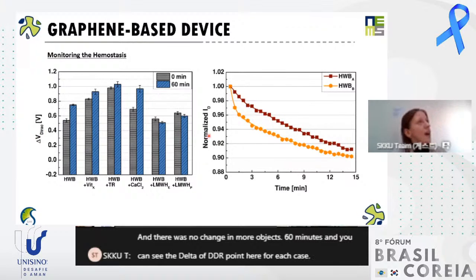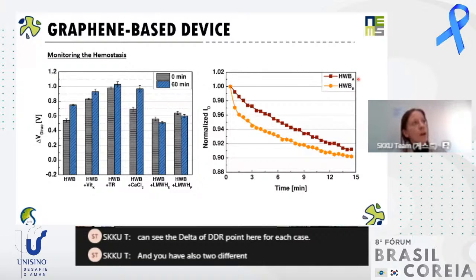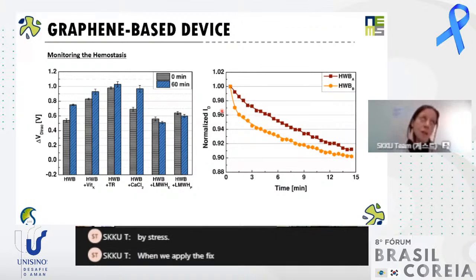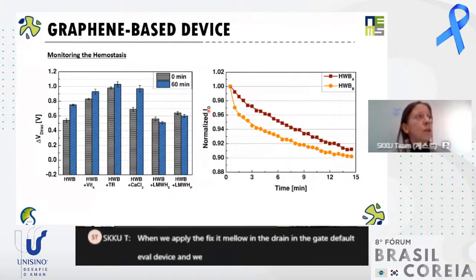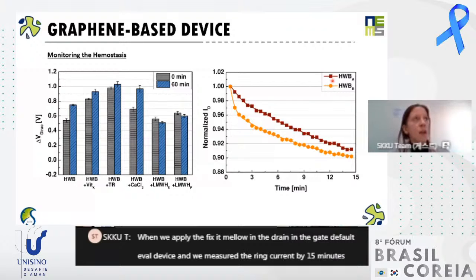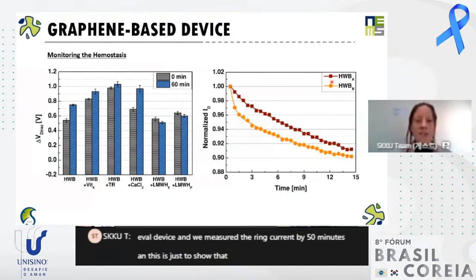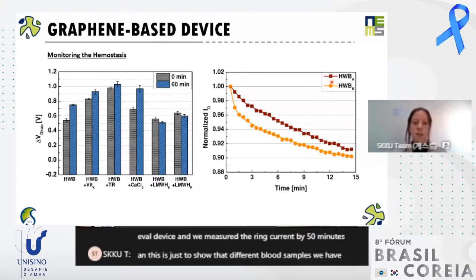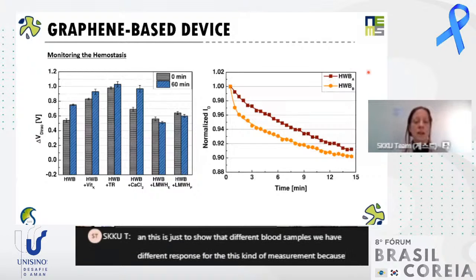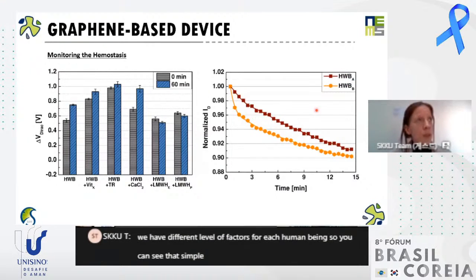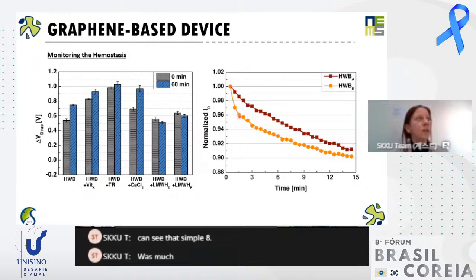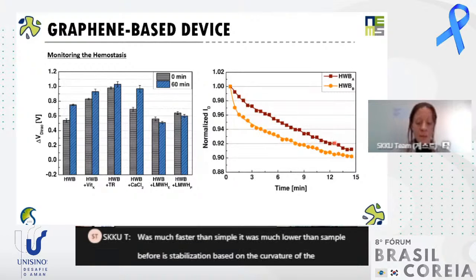And we also have two different samples that were evaluated by stress, where we apply a fixed value of voltage bias in the drain and the gate, and we measure the drain current for 15 minutes. And this is just to show that different blood samples will have different responses for this kind of measurement, because we have different levels of factors for each human being. So you can see that sample A was much slower than sample B for stabilization, based on the curvature of the drain current.